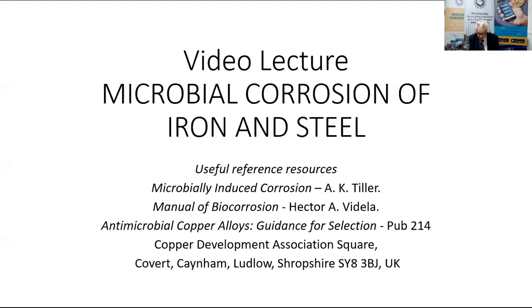also known as microbial or biological corrosion, is the deterioration of metals as a result of the metabolic activity of microorganisms. There are about a dozen, possibly quite a lot more, bacteria known to cause these microbiologically influenced corrosion of carbon steels, stainless steels, aluminium alloys and copper alloys in waters with pH values ranging from 4 to 9 and temperatures of between -10 and +50 degrees C.